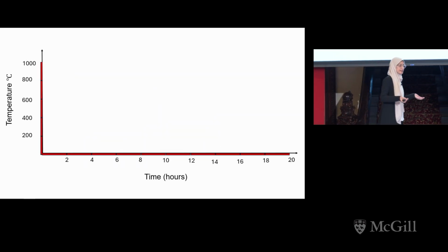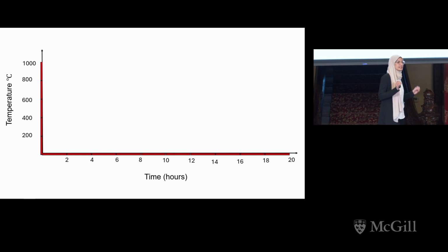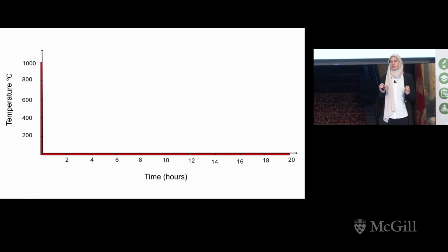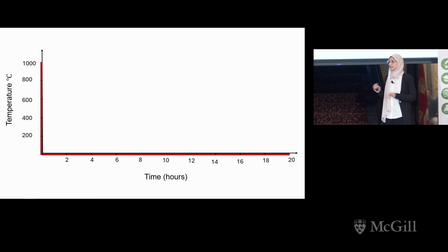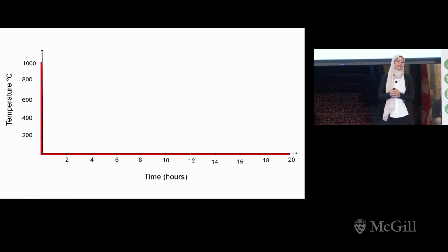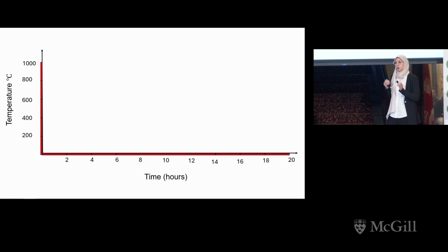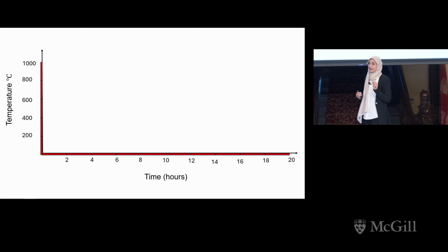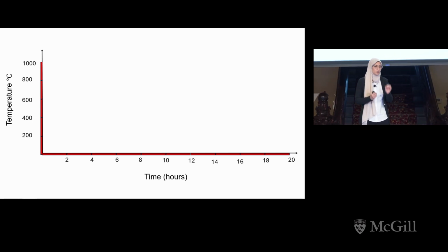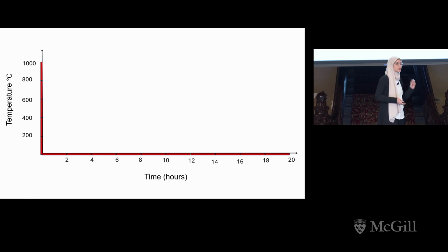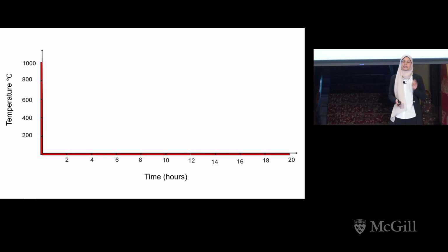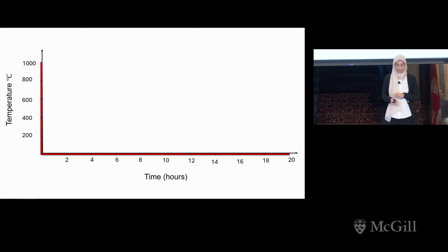When we looked into the literature, we found an interesting synthesis method called molten salt synthesis. People usually use this method to synthesize very large single crystals. We modified this method to make it able to synthesize very small single crystals, and this happened by applying two simple steps. Let me explain these steps to you.